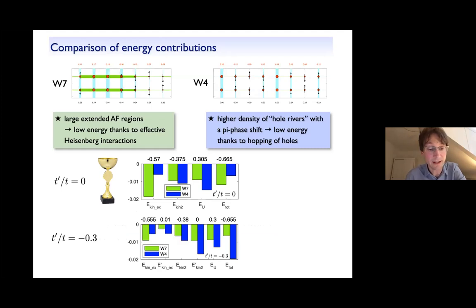And now, when we go to finite t prime, the finite t prime will induce a frustrating antiferromagnetic interaction along the diagonal, such that these large antiferromagnetic regions are no longer so favored, right? So the difference here becomes smaller, and on the diagonal, these are the diagonal antiferromagnetic contributions, you really pay a penalty. And the other kinetic contributions get more dominant, and at the end of the day, that's why the period 4 stripe wins over the period 7 stripe in this case, right? So you see it's a delicate balance of and competition between different energy contributions. A priori, it's not clear which one is going to win, but at least we can get some intuition why things shift in this direction.